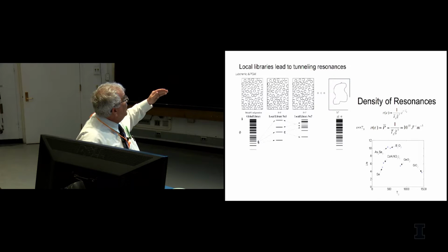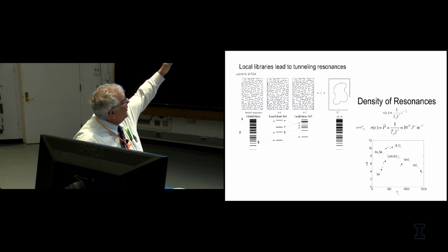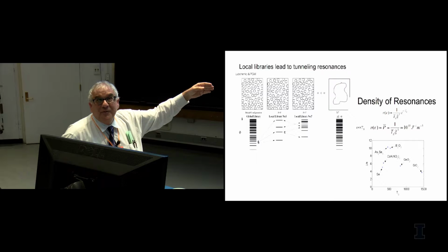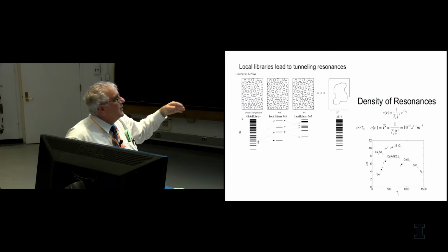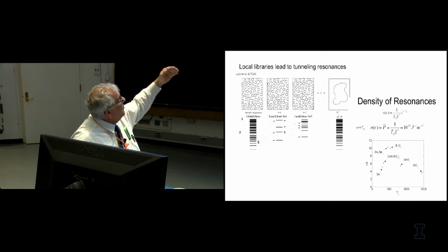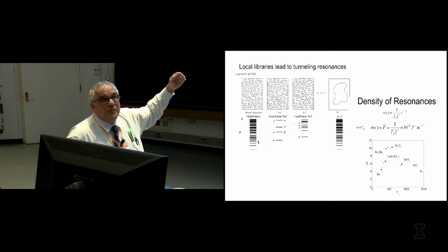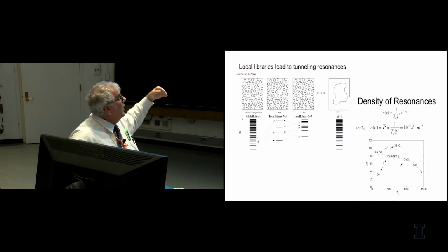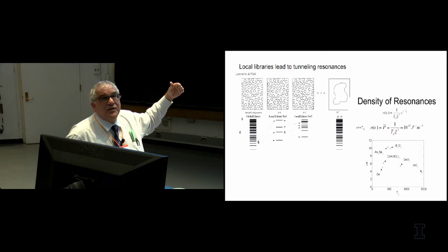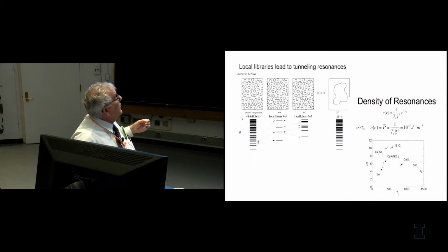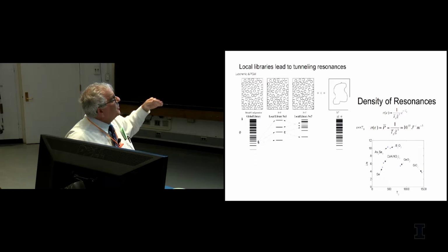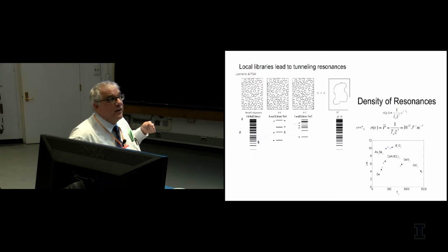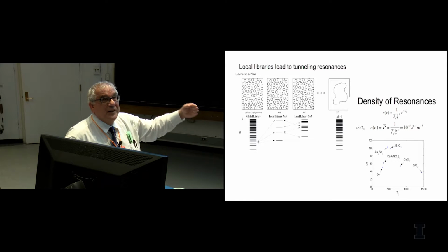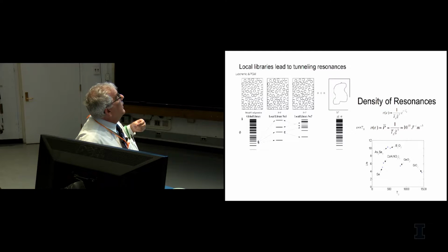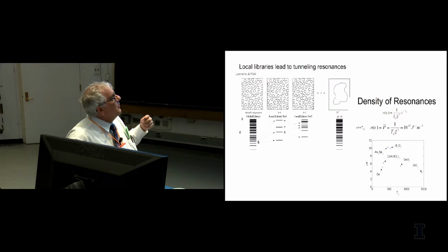As I said, you're growing these large numbers of states until finally you get over to the same state you had before, when you've rearranged the entire system. The size where you get to a state that's nearly resonant with where you were before is also roughly this correlation length. And you can now say that if you want to look at the distribution of states in the vicinity that you might be able to transfer through resonant tunneling, then it's basically something which is given by